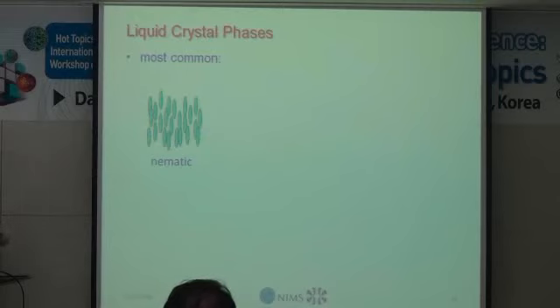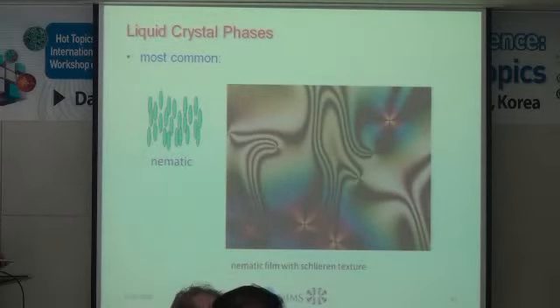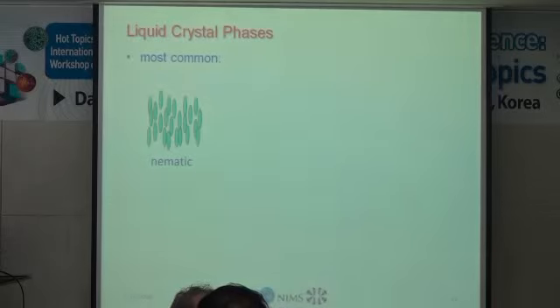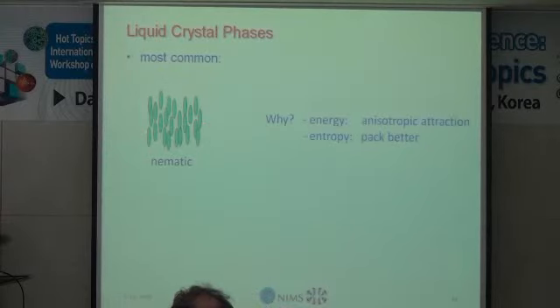Okay, so the most common liquid crystal phase is the nematic phase, where molecules or anisotropic objects simply point on the average in some direction, and you can get some really beautiful pictures in a polarizing microscope. And of course, these are the materials that are used predominantly in displays. And so why do they want to align like that? And it turns out that it's both due to the energy. They can minimize an energy by pointing in the same direction because of the anisotropic polarizability. And it turns out that entropically they're also favorable because they can pack better. So even though they give up degrees of freedom of orientation, they can move around in position space better, and so entropy favors it as well.